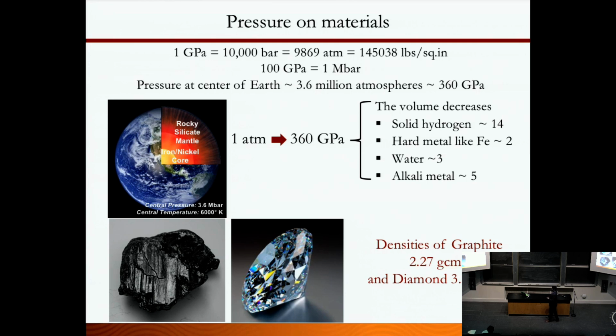So it's not really a surprise, it's the densities. If you look at the density, graphite is 2.27, but diamond is almost 3.5. It's much denser than graphite. So under pressure, the driving force is to make the material denser, to get into a more dense form.